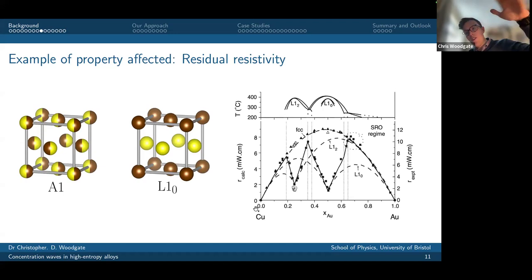If I quench the solid solution from high temperature and look at the residual resistivity, I get these triangles, this dashed curve here, so I get this nice parabolic behavior where at pure copper or pure gold, I have a pristine crystal and my residual resistivity goes to 0. In between the two, it has this x times (1 minus x) parabolic type dependence.